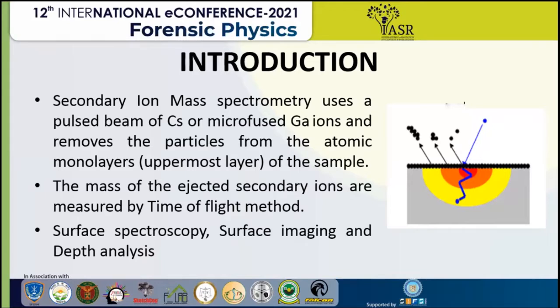This is a surface-sensitive analytical method. It provides elemental and molecular information at very low detection limits in the range of parts per million or even parts per billion under optimum conditions. This instrument can measure and identify all elements of the periodic table from hydrogen to uranium, along with its molecular species, ions, and even isotopes.